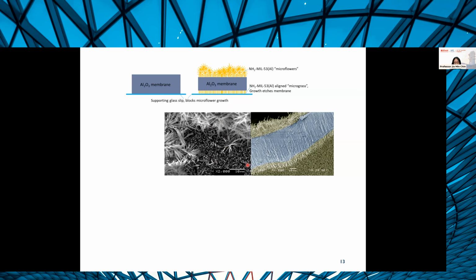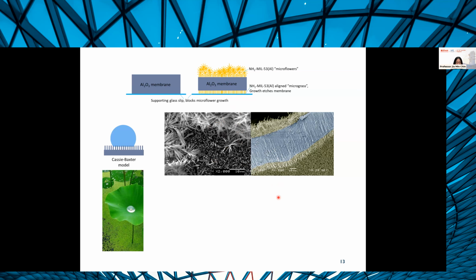But then at the bottom, because you have this glass slip, it blocks the microflower growth. And you end up with this monolayer of very nicely aligned micrograss. And when we looked at it, we thought, okay, this is actually reminiscent of a Cassie-Baxter model for a superhydrophobic surface. That is classically used to describe surfaces like the lotus leaf, which is a well-known superhydrophobic material. And so we thought, okay, maybe we could make these materials superhydrophobic.